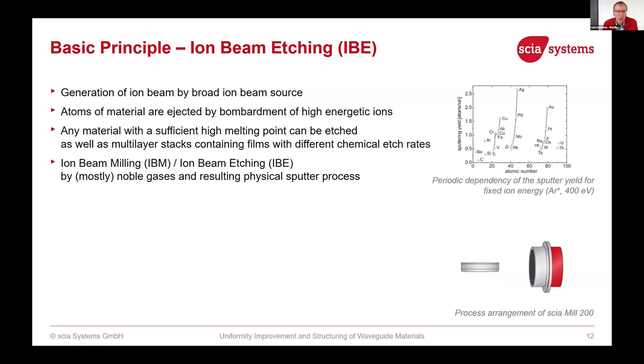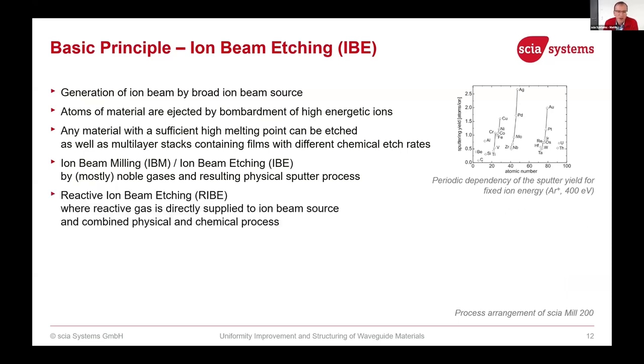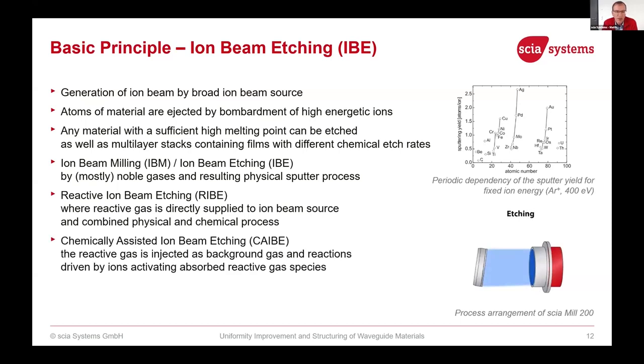We call it ion beam milling or ion beam etching when we just apply noble gas in the ion beam source. So we hit the surface with noble gas ions like argon. But we can also apply reactive gas in such a process. Then we call it reactive ion beam etching. So we increase the etch rate and some selectivity. And further improvements can be achieved by so-called chemically assisted ion beam etching. That is a mix of noble ion irradiation plus a chemical substance which is fed close to the substrate, to the surface.